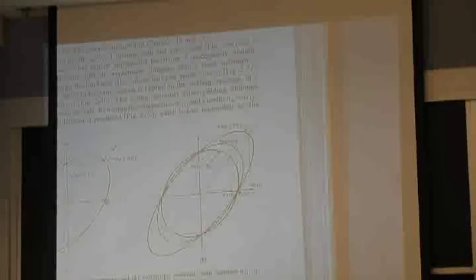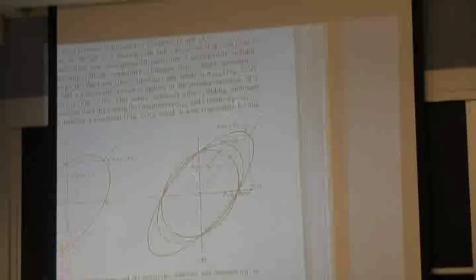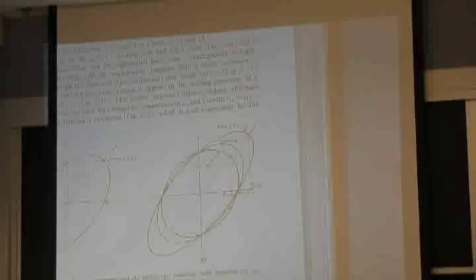And in fact, we find that real materials are not isotropic. They can have ellipses that have large major axes versus minor axes, or they can have the opposite, and you can have positive or negative deviations from isotropy. It turns out that if I want to do sheet metal forming, I like to have long axis ellipses, things that are good in balanced biaxial tension, that become stronger. Look at this. This material is strengthened by pulling it at the same time in the two directions. This is the yield strength for uniaxial. This is the yield strength for balanced biaxial. It's higher. It's stronger when I pull it in both directions.